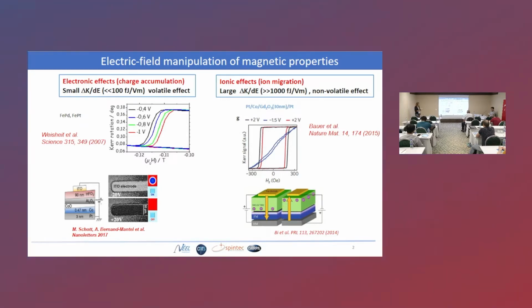But more recently, magneto-ionic effects have been shown to give rise to much larger variations of magnetic anisotropy, and I show here in particular the work of the Beach group on platinum cobalt bilayers covered by a gadolinium oxide layer that is known to be an oxygen ionic conductor. In this case, they managed to show that they can change anisotropy by an order of magnitude larger than with electronic effects or more, so that the magnetization can be switched from out of plane to in plane, and then in a reversible way back to out of plane.